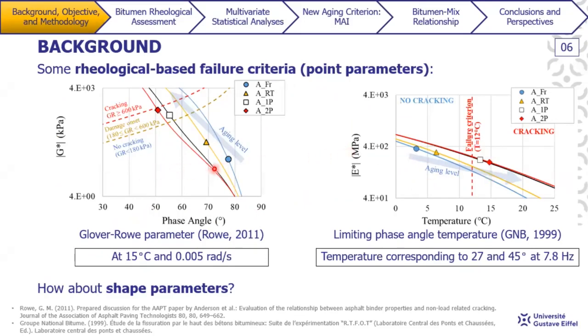And in both cases, although we have all the rheological information here that is represented by the curves, we only look at one single value here at a given condition. For Glover-Rowe, it's at 15 degrees Celsius and 0.005 radian per second. Whereas for this one, actually, we have two parameters. We have the temperature corresponding to the phase angle of 27 or 45 degrees, both at 7.8 hertz.